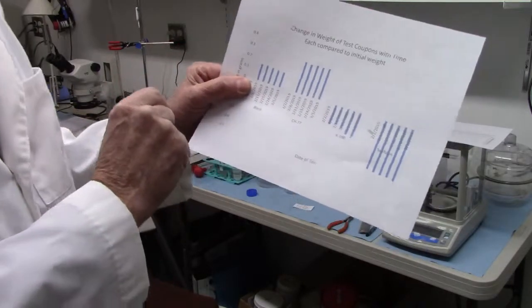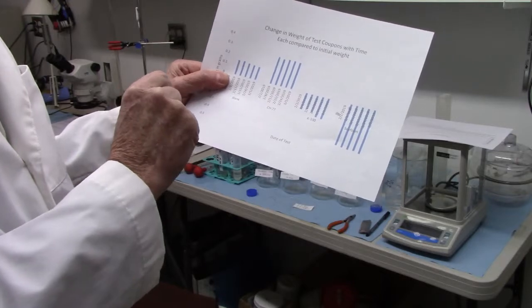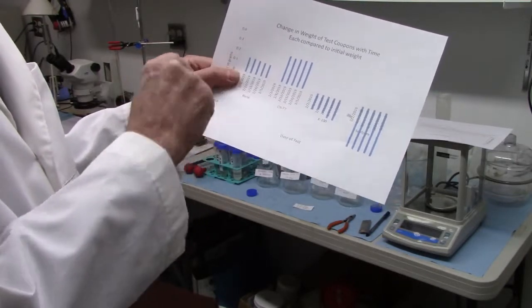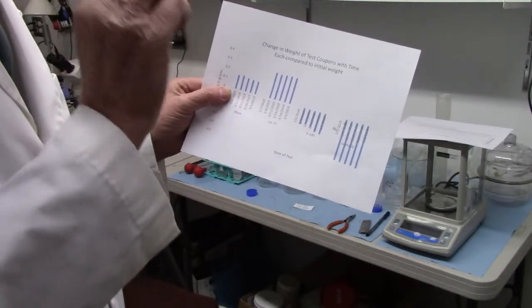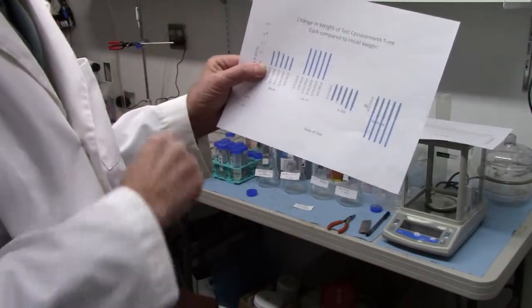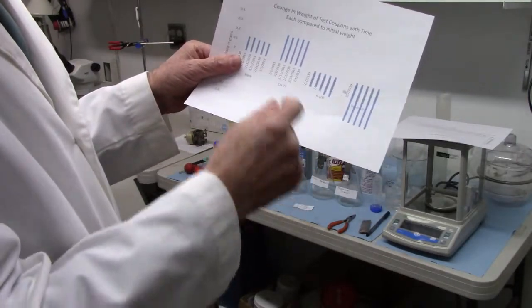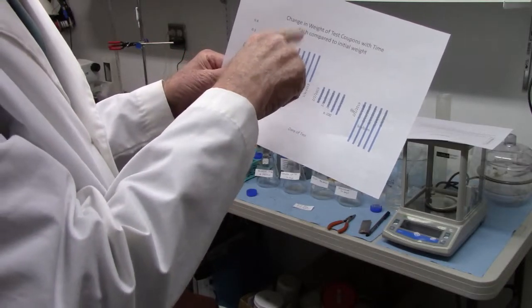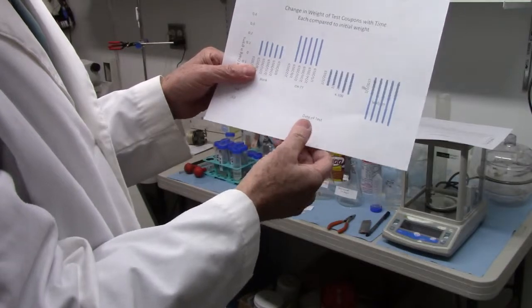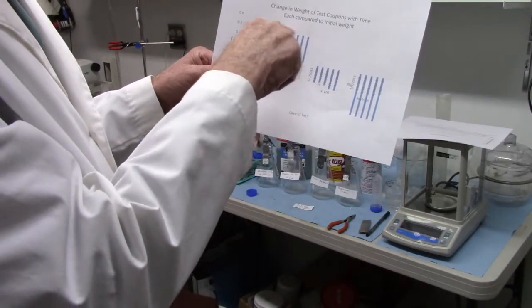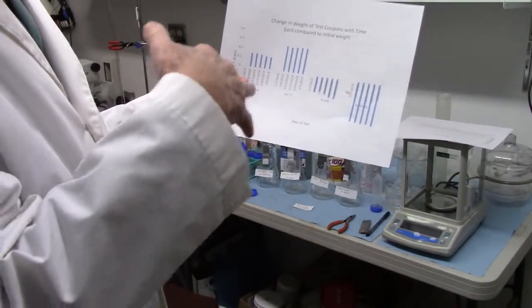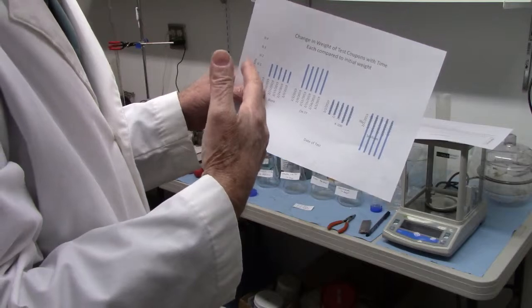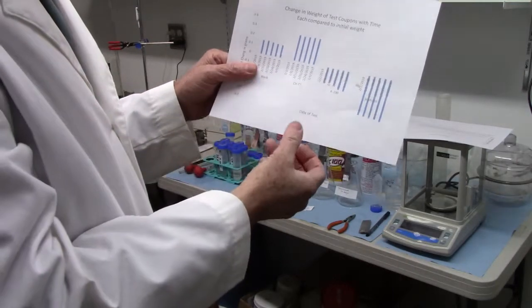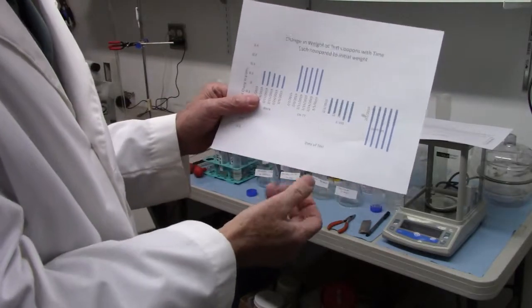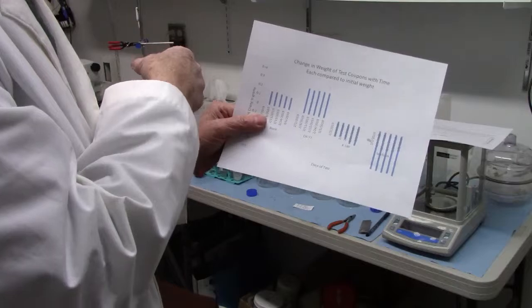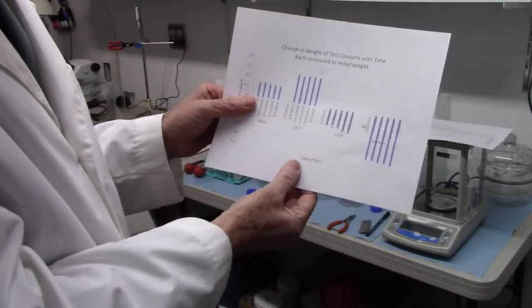My guess is it actually remained constant because the corrosion was so heavy on the surface that the corrosive chemicals couldn't get to the metal surface to corrode it any further. The CH-77 also increased in weight by nearly 300 milligrams per coupon, and remained pretty much constant. So it appeared that the surface acquired a layer, and my shrewd interpretation is that it acquired a layer of the corrosion inhibitor material that is part of the formulation. I know exactly what's in there, but I'm not going to tell you.